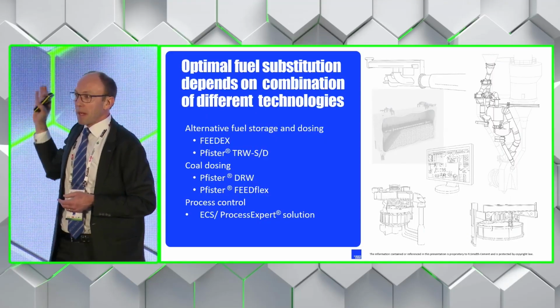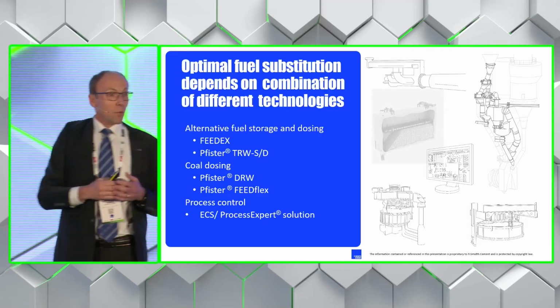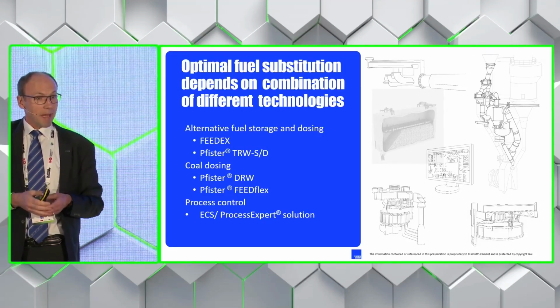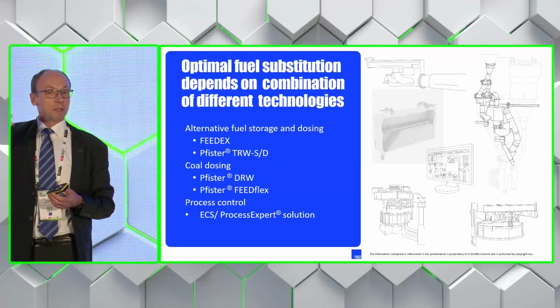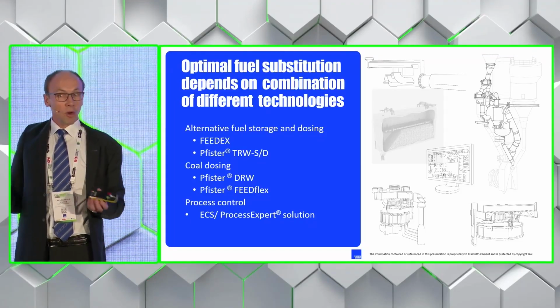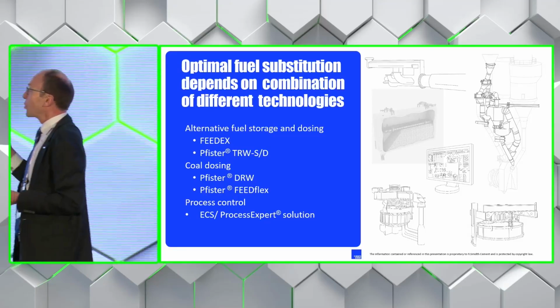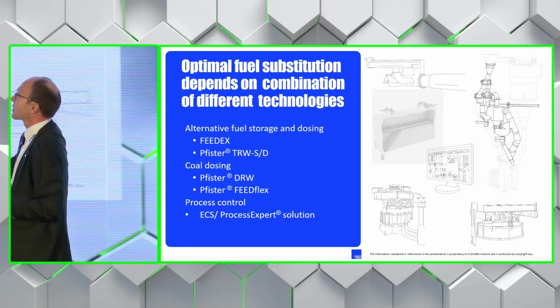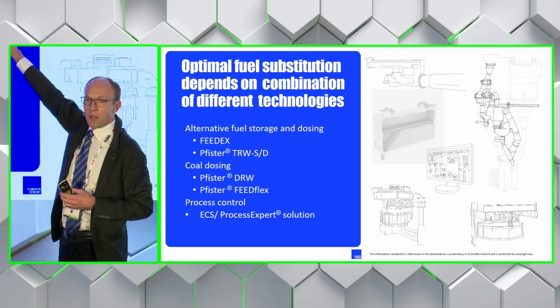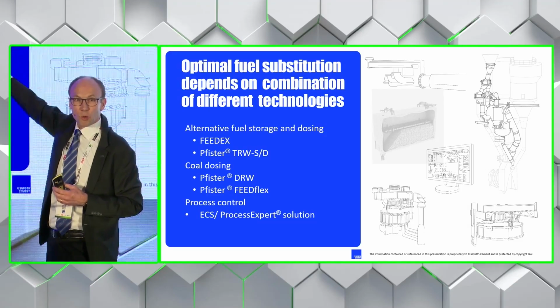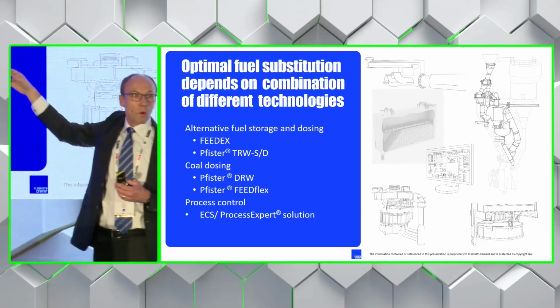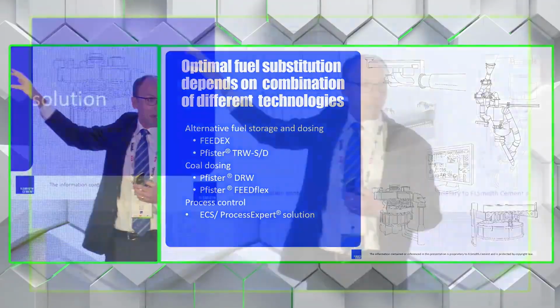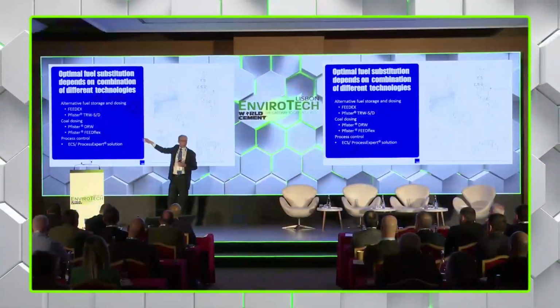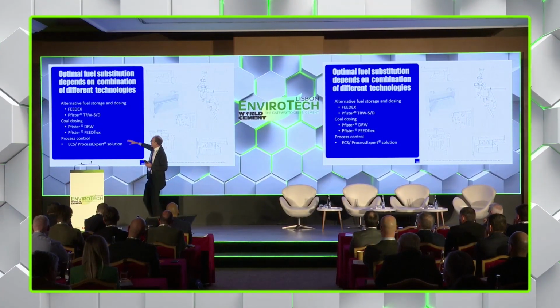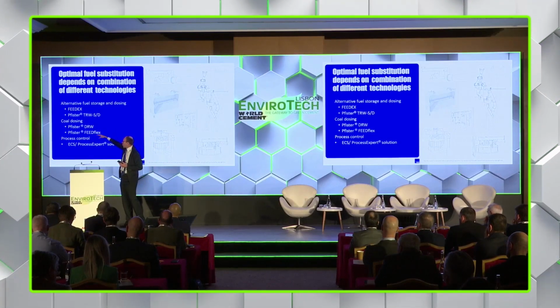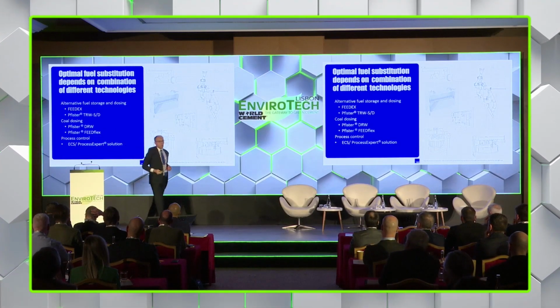As I mentioned, we had reached 80 to 90% substitution at Mannok, but then the targets were lifted now. Now they wanted to get rid of all of the coal in the calciner. To do this, we needed to look at what were the bottlenecks. We had the alternative fuel dosing, which couldn't quite substitute all of the fuel. So what we did there was to debottleneck the mechanical feed system and to boost the Pfister feeders feeding the alternative fuel. In addition to that, we then looked at the coal dosing and the overall process control.